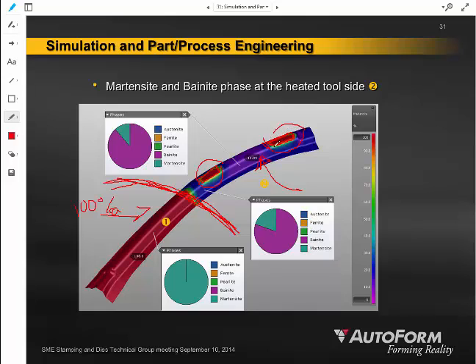And where the blank was resting on this tool, it was acting as a heat sink, and it was drawing heat out of the tool at a faster rate than did the rest of this A pillar, where we have some ability to put cooling channels or heating channels through the die in order to maintain the 400 degrees Celsius temperature. So the rest of this A pillar was being maintained at 400 degrees C, except for the little spring-loaded pads that were controlling this blank's orientation during the loading.